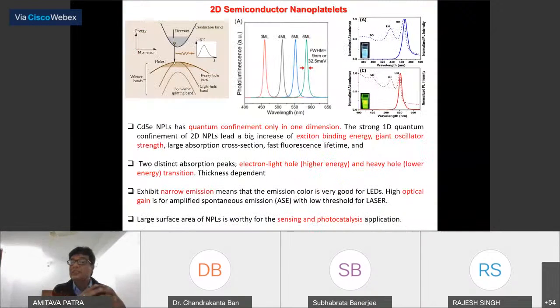Now, so far I discussed the quantum dot, where you can change the size and you can tune the color from blue to green to red by changing the band gap. But this is a 2D semiconducting nanoplate. This is the band diagram where you have the heavy hole and light hole, because this band diagram is parabolic, because quantum confinement is one directional, because it is a 2D structure. In that case, we have seen that if you change the number of layers, maybe 2 layer, 3 layer, 4 layer structure, you can tune the emission band, that is 3 layer, 4 layer, 5 layer, from 450 nanometer to 600 nanometer. You can tune from blue to green to red.